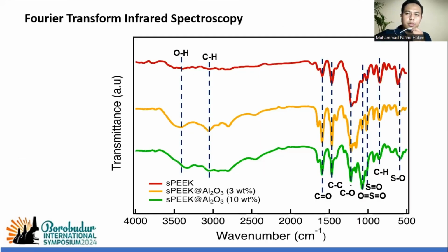Then after SEM, we can make sure about the highest proton conductivity with FTIR, about the functional groups. We can see together many functional groups identified from these membranes. The FTIR characterization of the 10% sPEEK aluminum oxide membrane is presented in this figure, and the wave number and intensity of the 10% sPEEK aluminum oxide membranes can also be displayed in a table, but in this presentation, I just show you with this graphic.